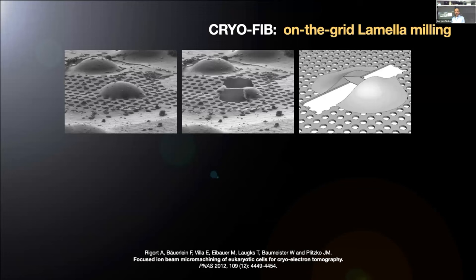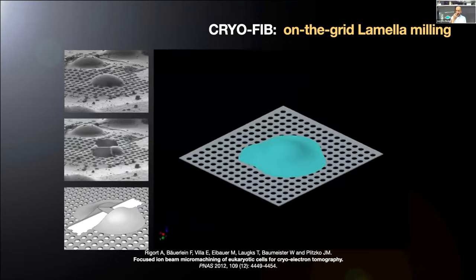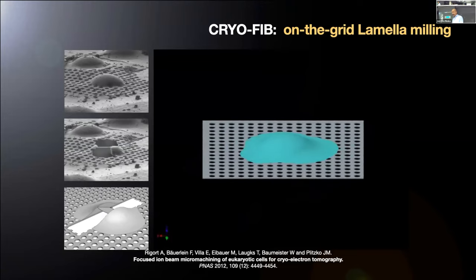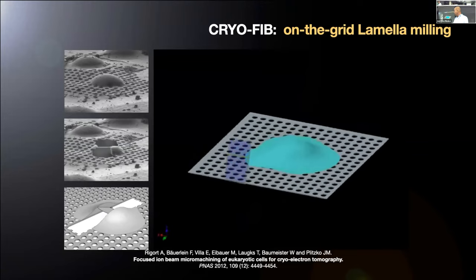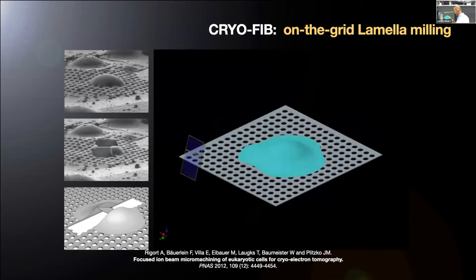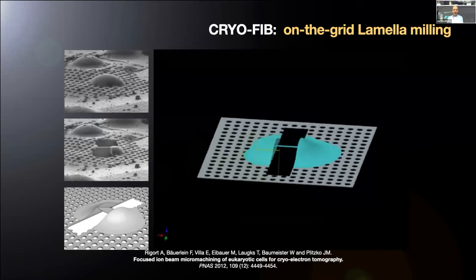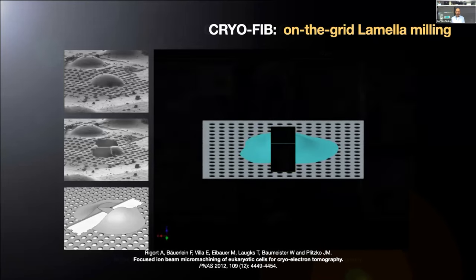And we came across the idea that you can use a cell, and see one cell on the left, cut open from the top, cut open from the bottom, and in the sketch on the right you see a freestanding lamella. This is depicted in that little animation here, because sometimes it's hard to understand what you see here. So you cut a pattern from the top with the gallium beam, you cut from the bottom, and you have a 100 or 200 nanometer thick lamella freestanding, no support film anymore, for doing tomography.